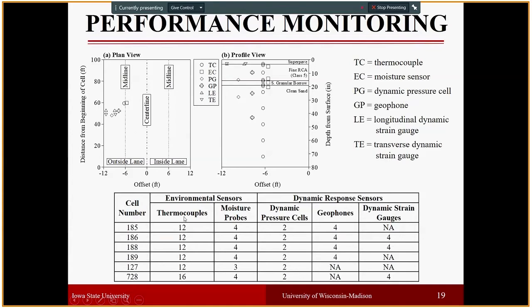The majority of the sensors are placed in the recycled concrete aggregate bases. Cells 185 through 189 are all the recycled aggregate base test sections, and we have one on the large stone subbase and at the end of the geosynthetic test section. The sensors are placed on the outside lane, not in the inside lanes, and we have thermocouples placed all the way up to 70 inches, which is almost 6 feet depth. And we have moisture sensors that are close to the ground surface.